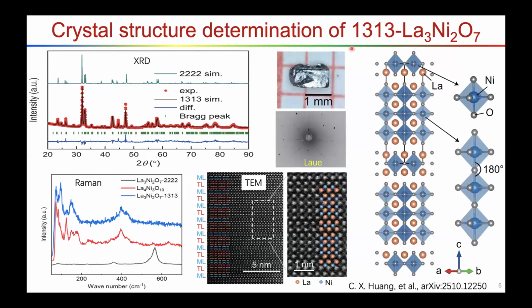spent lots of time to grow high quality 1313 single crystals, using a high pressure floating zone furnace. Here's our single crystal, and this is a schematic of the structure. So we can test the structure by XRD, by Raman, by Laue, and the TEM. All the measurements confirm our single crystal is this 1313 phase. Okay, so we can clearly distinguish the structure by all the techniques. But we can always ask whether it's a pure 1313 phase or only a small region with this phase.